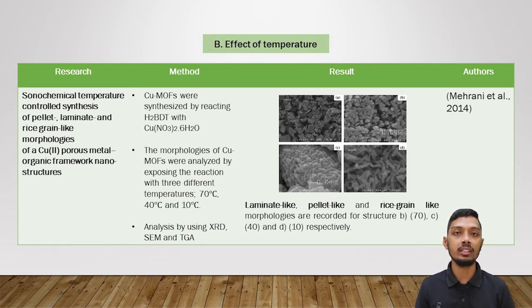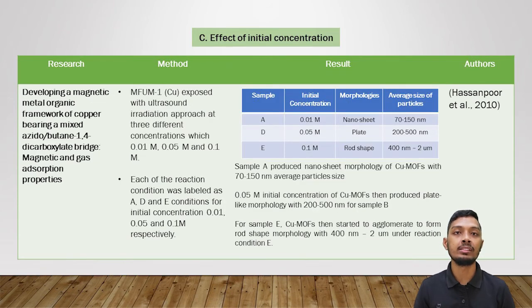And then we will move on to the third and last effect of parameter, which is the effect of initial concentration. In 2010, Hassanpoor et al. have synthesized copper metal organic framework using three different initial concentrations, which are 0.01 molar, 0.05 molar, and also 0.1 molar. Each of these synthesis conditions was labeled sample A, sample D, and sample E respectively. The result revealed that sample A with initial concentration of 0.01 molar will produce nanosheet-like morphology with 70 to 150 nanometer. Sample D with 0.05 molar of initial concentration will produce plate-like morphology with average particle size of 200 to 500 nanometer of copper metal organic framework.